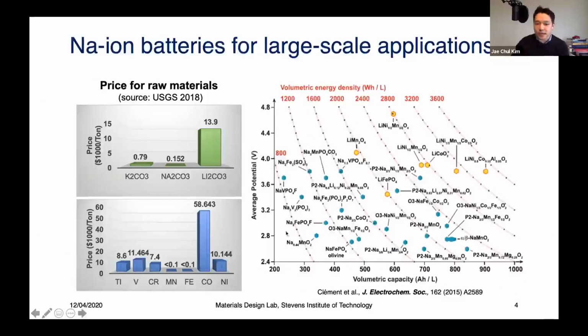Yeah, that's a great question. If you look at this energy density plot, it is somewhat outdated, published in 2015. But if you see all these sodium battery materials here, many of them still contain cobalt. That's because cobalt is such a magical material. It stabilizes the octahedral layered structure perfectly. So our goal is to stay away from cobalt and use manganese and iron most of the time. We're getting there, but not yet.